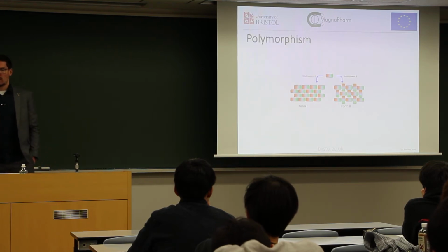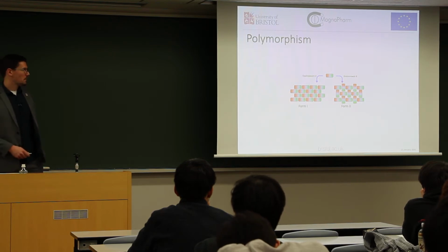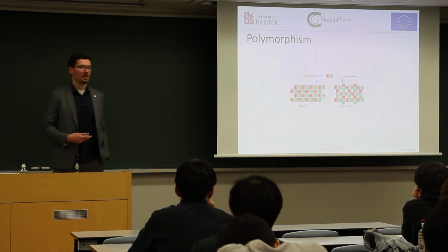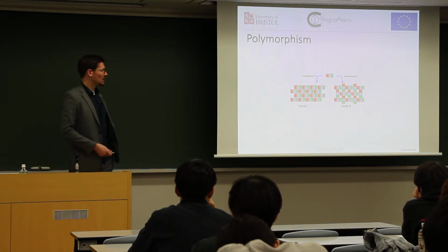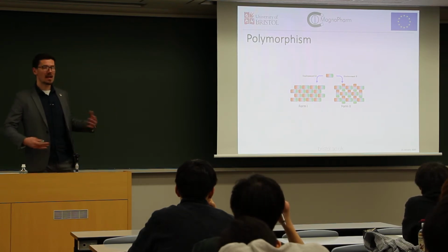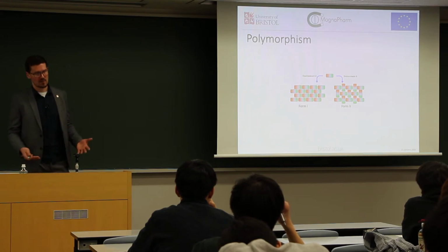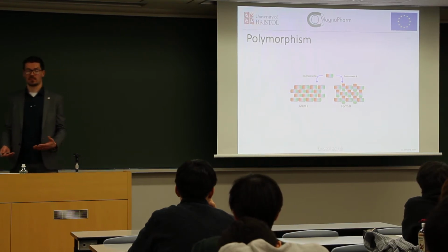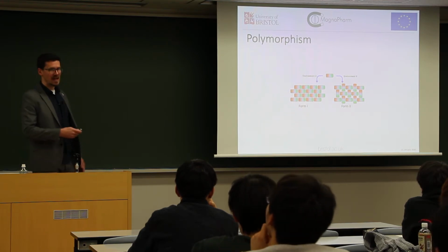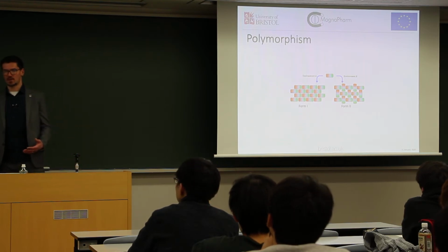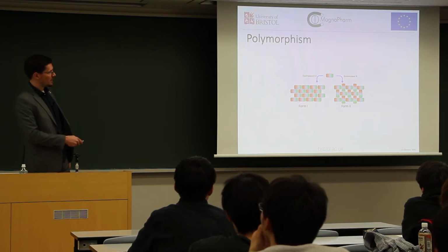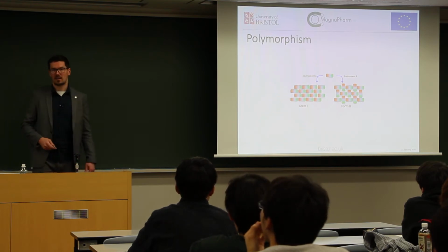Polymorphism is really where my specialism is, and that is effectively the ability of a molecule to pack in a number of different ways, not just the most efficient, so the densest. Any molecular crystal can pack in a number of ways if exposed to the right parameters, the right variables. So, for example, in environment A, let's say we use physical vapor transport, we get this packing, and if we recrystallize it from ethanol, environment B, we get that kind of packing.